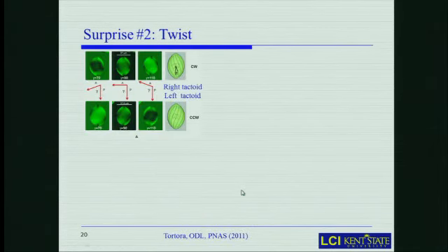Another interesting thing was that by observing them between the two cross polarizers, we realized that if the axis of the tactoid is oriented parallel to one of the polarizers, it's not going to become dark. You see that when the analyzer and polarizers are perpendicular to each other and one of them is parallel to this axis, the central part of the tactoid is bright.